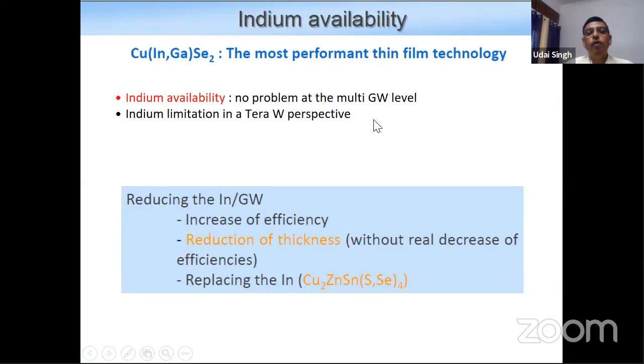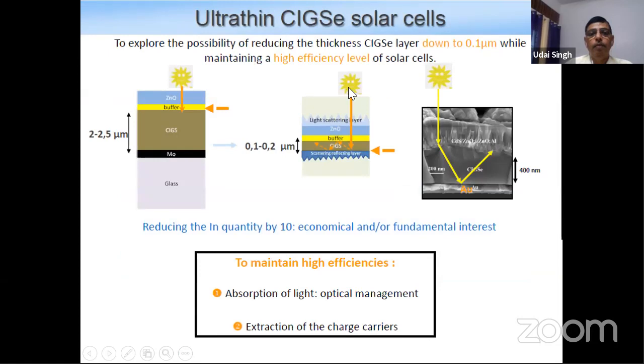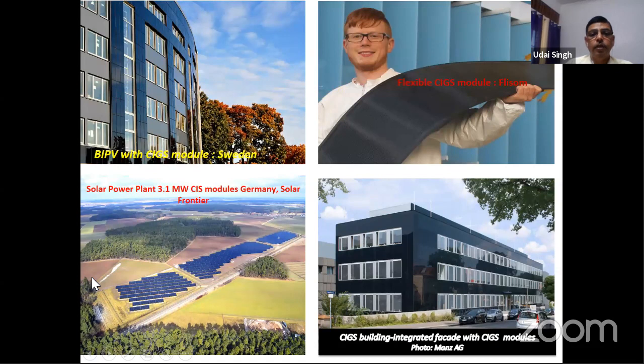Now people are thinking that if you want to go for terawatt or gigawatt scale, the problem may come with indium. Indium availability at gigawatt level is not a problem, but when you go to terawatt, it may be a limitation. So people try to see what other alternatives there can be. They try to replace indium with zinc and tin, so you get copper zinc tin selenide. What is the CZTS? People have also tried ultra-thin CIGS, but manufacturing is difficult. At lab scale you can get it, but manufacturing is still a big problem. These are some of the applications of CIGS solar cells around the globe.